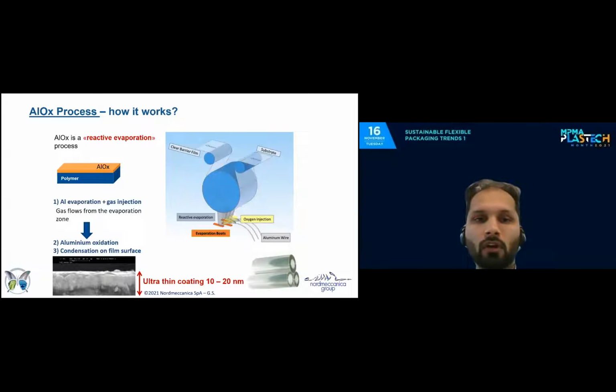AlOx is a reactive evaporation process. Here, what we have is a combination and a reactive evaporation between the aluminum evaporation and the oxygen injection. The combination of these two generates aluminum oxidation. And this aluminum oxidation condenses on the film substrate, generating a clear barrier web.